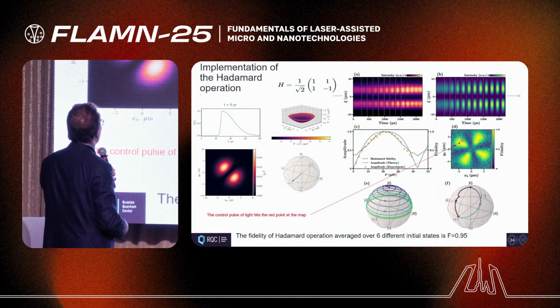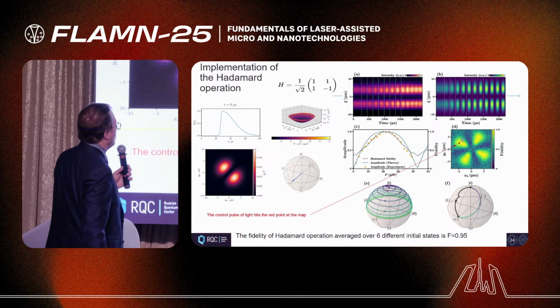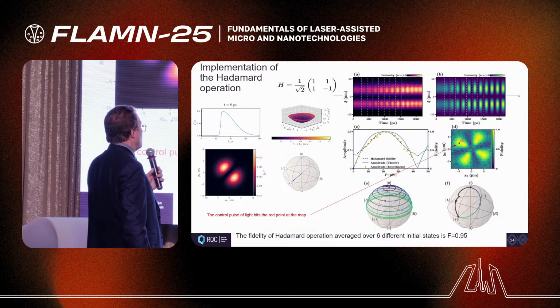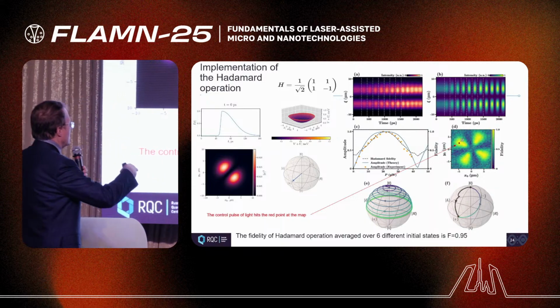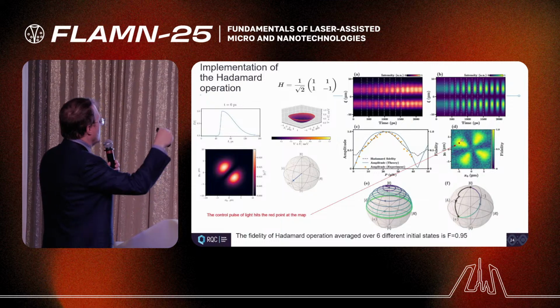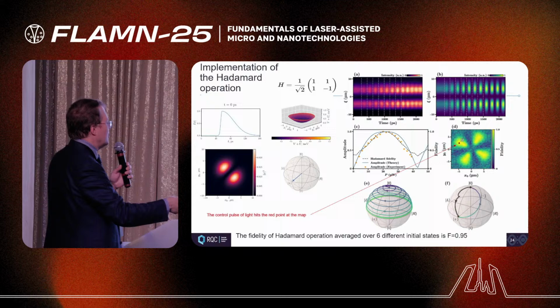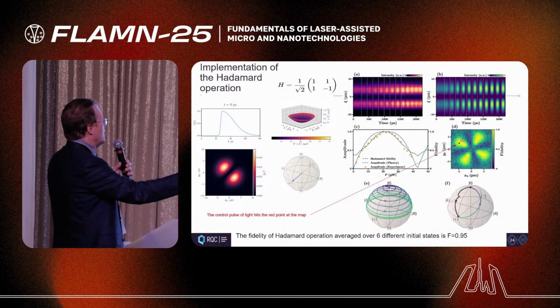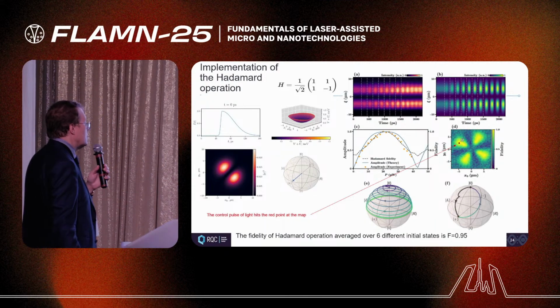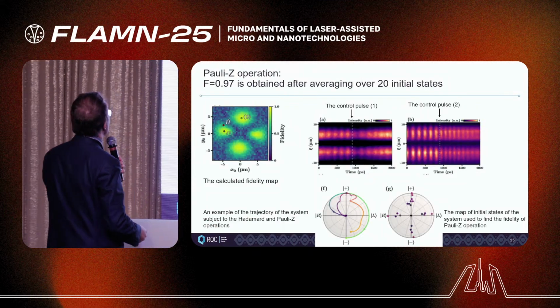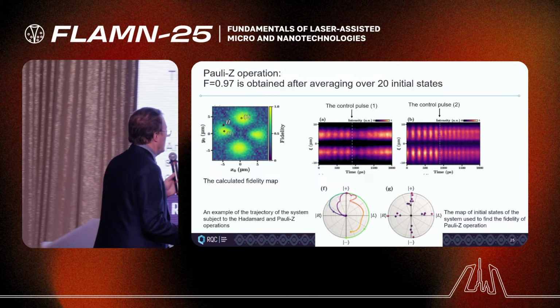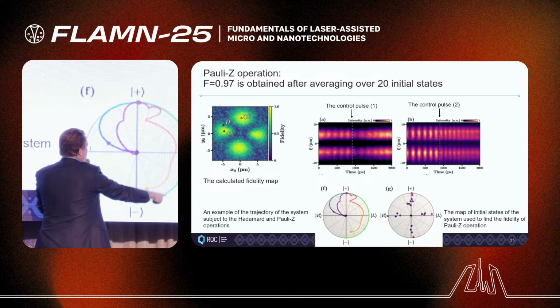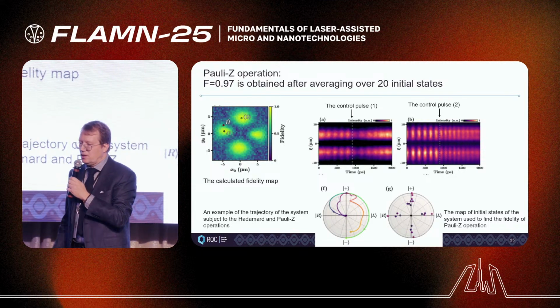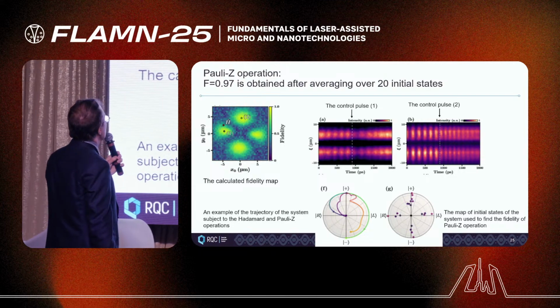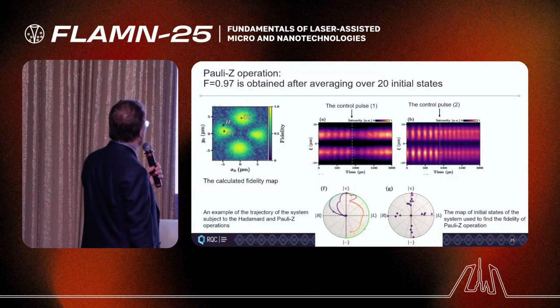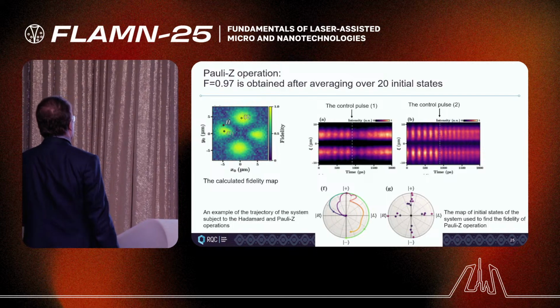So here, for example, for the Hadamard operation described by that H operator on the top, we obtain a fidelity of 95%, averaged over 6 different initial states. So we probe different initial states on the Bloch sphere. We always use the same gate, the same control pulse, and we see how much the result deviates from the predicted one. This gives us the fidelity, so 95% for this operation, and even more, 97% for the Pauli Z operation, which corresponds to a 180 degree rotation around the axis of the Bloch sphere. Here the experiment was done very carefully with 20 initial states examined. So this fidelity is approaching the fidelity of superconducting gates already.